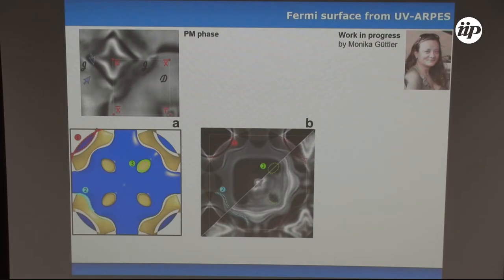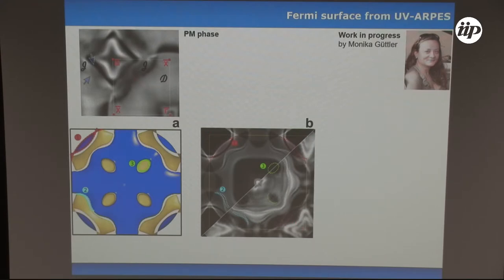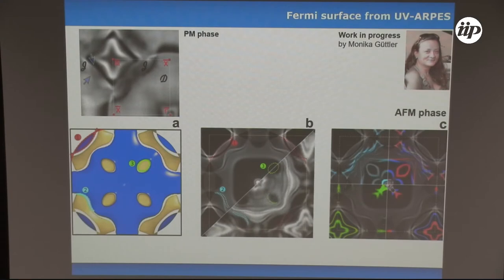Later on we performed ARPES in the antiferromagnetically ordered phase at 10 K. We were a little puzzled because rather than a homogeneous band structure, we could see plenty of splittings. You can also detect the large donut, but there are many additional bands. The surface state at the endpoint also becomes split, implying all of this is related to magnetic order of the system. Interestingly, bulk calculations do not propose any splittings of the bulk states. Making slab calculations and comparing the data, we found that bulk states seen at different terminations become split after the transition to the magnetically ordered state due to exchange coupling. The surface state is also split, with the first magnetically ordered europium layer lying four layers below the silicon surface.